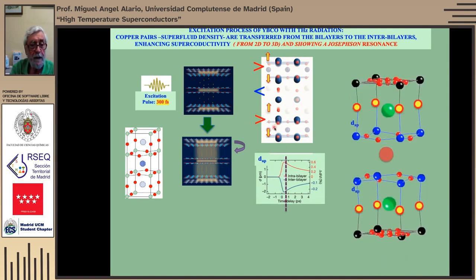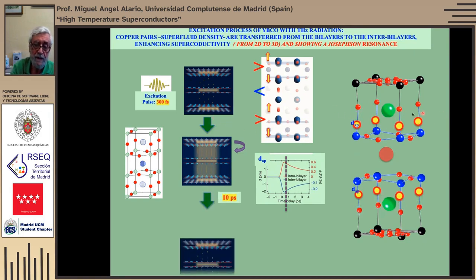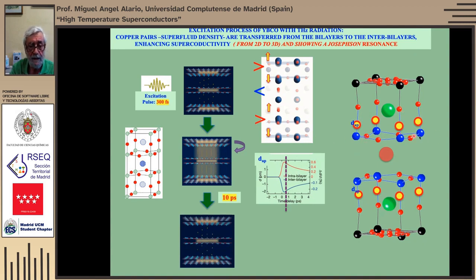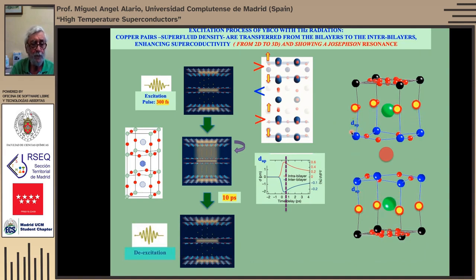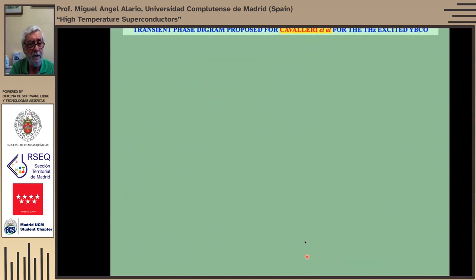Well, we represent this in the structure. This is a cartoon that I made myself. When you send the pulse and the excitation goes to here, these oxygens get close to the copper here. And this, the apical distance, is the crucial bond that you can actually change when you send a pulse of terahertz spectroscopy. Okay, and then as it is very brief, when there is a de-excitation, the atoms go to the original position. So in that brief moment, you have superconductivity, and at the end, as you can see, the distance will go back to the origin. So it's a transient process.